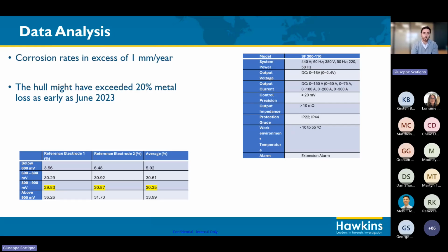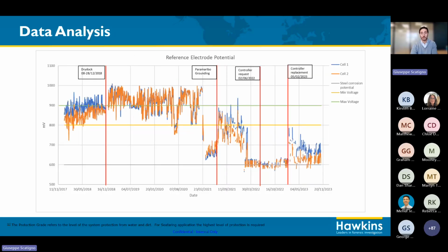Now, why is it important that we don't exceed the higher threshold as well as the lower threshold? Because if we exceed the higher threshold, we go into a process known as spalling. So what can happen is that effectively, by overprotecting the metal, we allow the protective coating on the metal substrate to be removed. And then at that point, not only are we in an area where we are not protected against corrosion, we don't even have a coating that we can rely on to slow down corrosion.